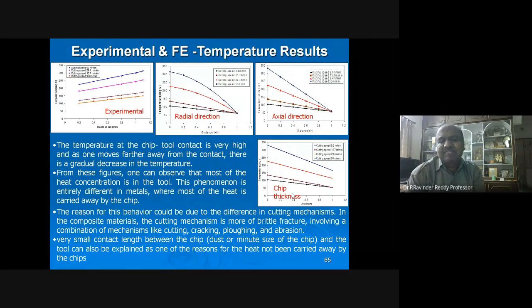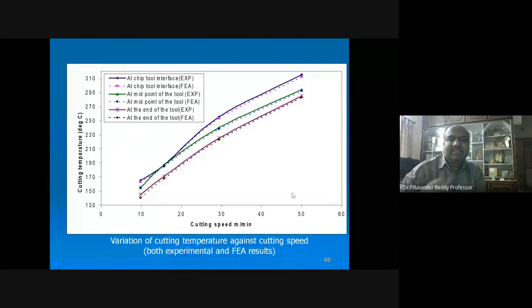The reason for this behavior could be the difference in cutting mechanisms. In composite materials, the cutting mechanism is more of brittle fracture, involving a combination of mechanisms like cutting, cracking, ploughing, and abrasion. These are the four mechanisms observed in the cutting process. The very small contact length between the chip, dust or minute-sized chip, and the tool can also be one of the reasons for the heat not being carried away by the chips.